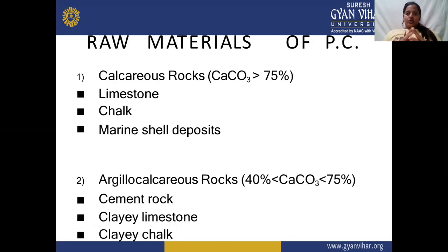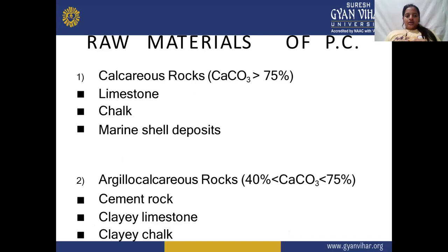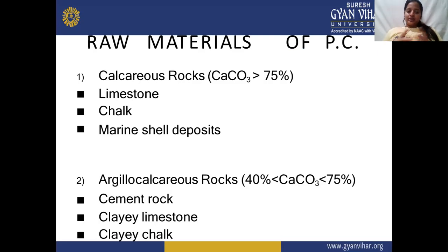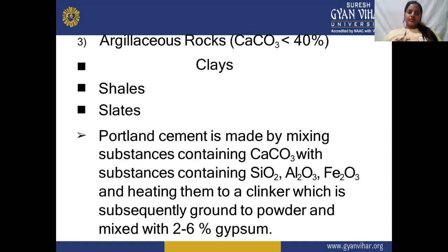The raw materials for Portland Cement: first is calcareous rock, which is CaCO3, around 75%, used in Portland Cement. Sources include limestone, chalk, and marine shell deposits. The second type is argillo-calcareous rocks, which are around 40% to 75% CaCO3, with sources being cement rock, clay limestone, and clay chalk. Then argillaceous rocks, which are less than 40% CaCO3, which include clay and shale.